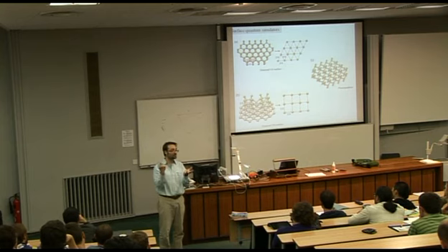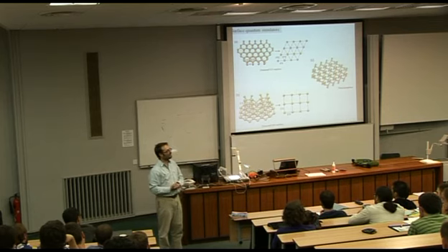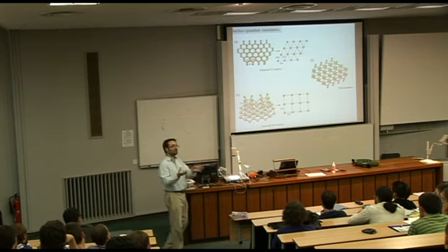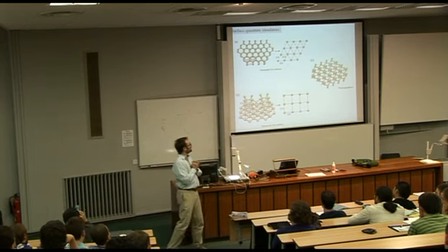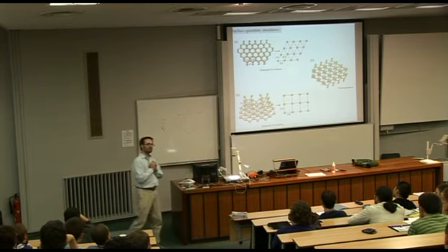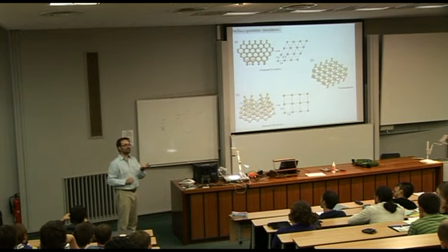Carbon-13 has a nuclear spin, and so we would have this nice hexagonal lattice of carbon-13 spins. Then we thought, we will manipulate it with our NV center, and we have a wonderful quantum simulator. Until we remembered one thing, namely graphene has no band gap, so it absorbs a lot of light.